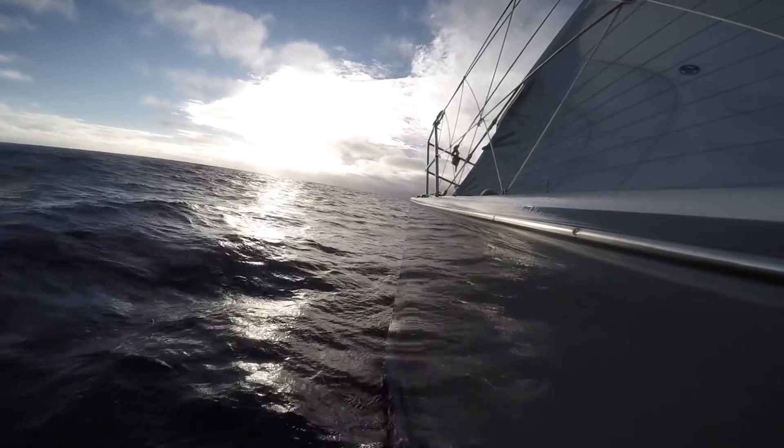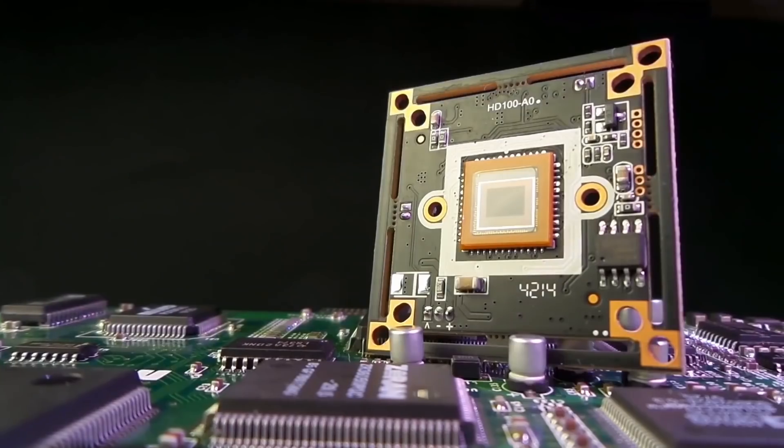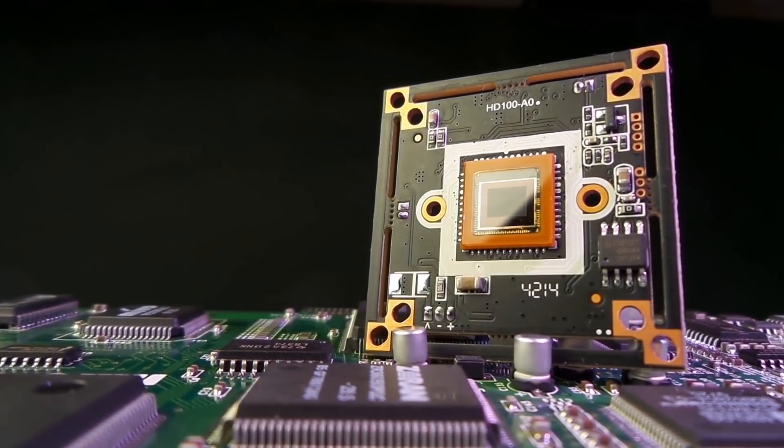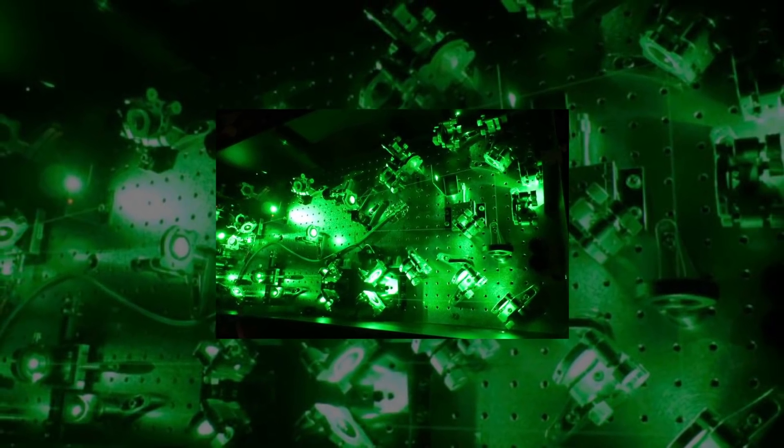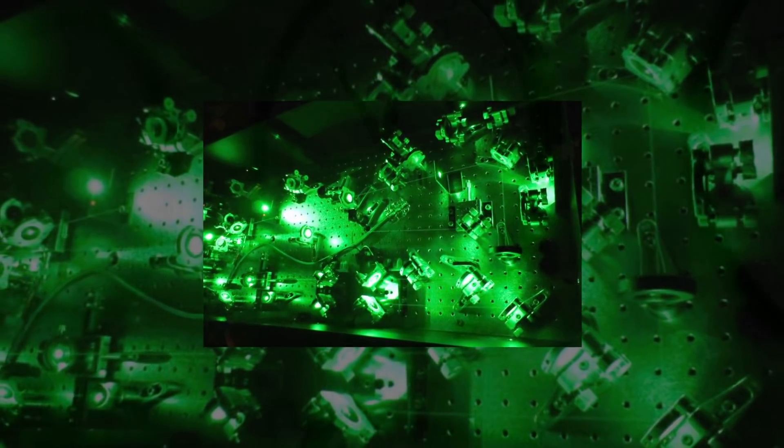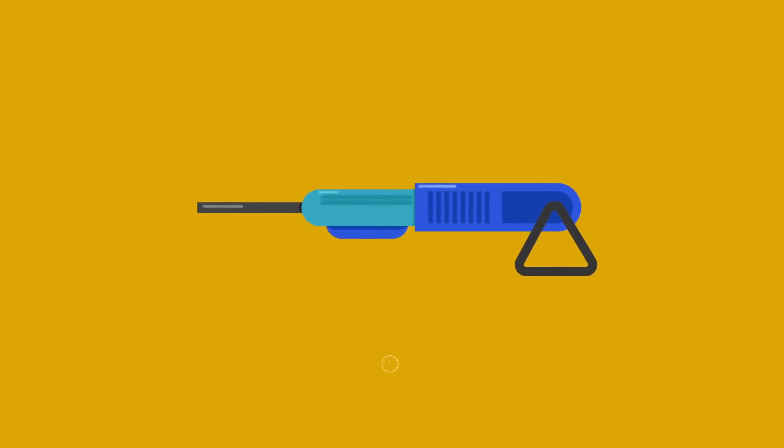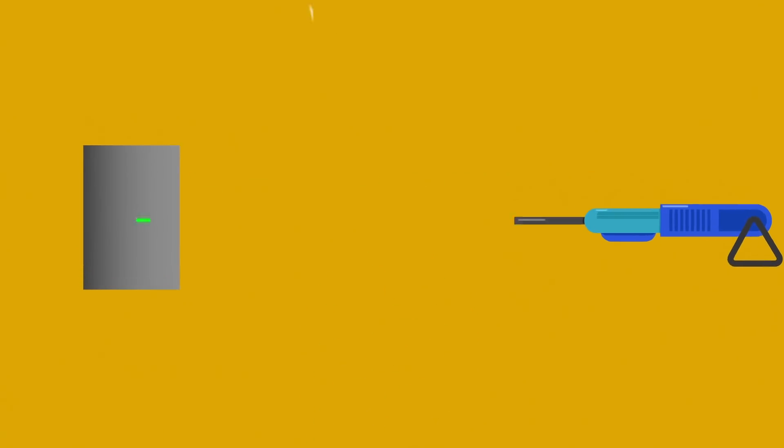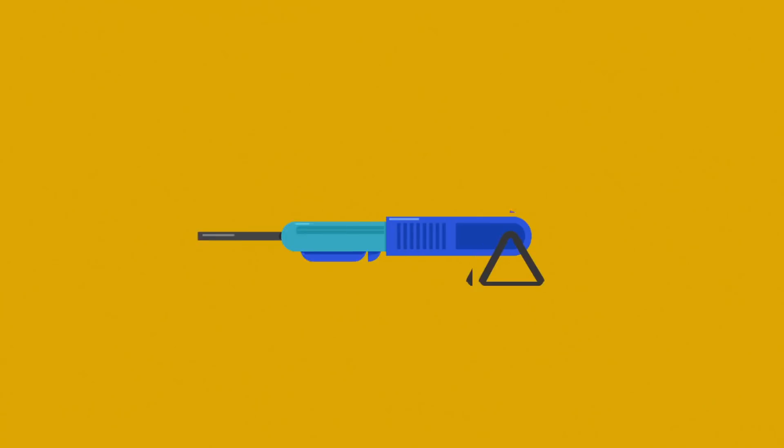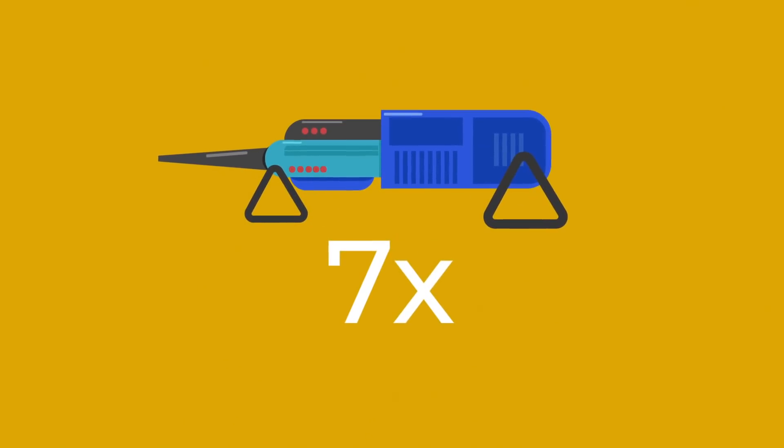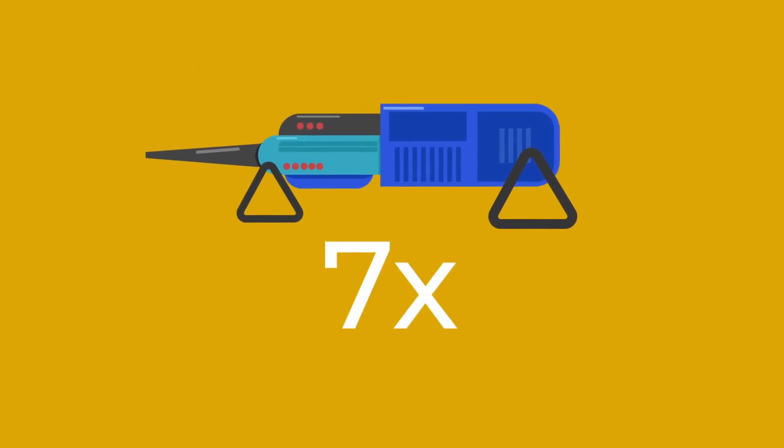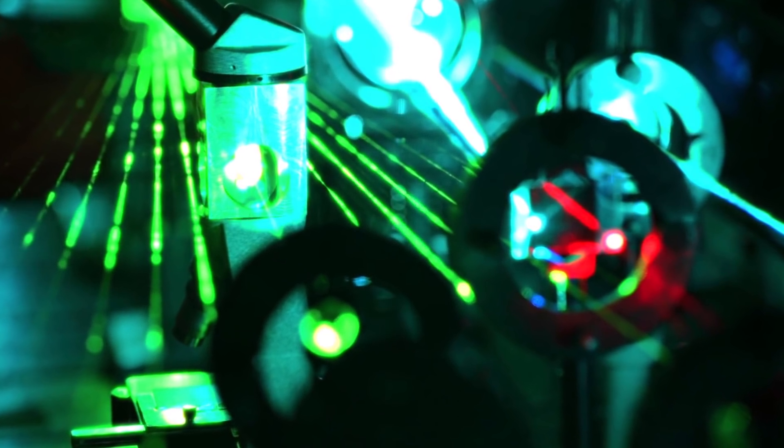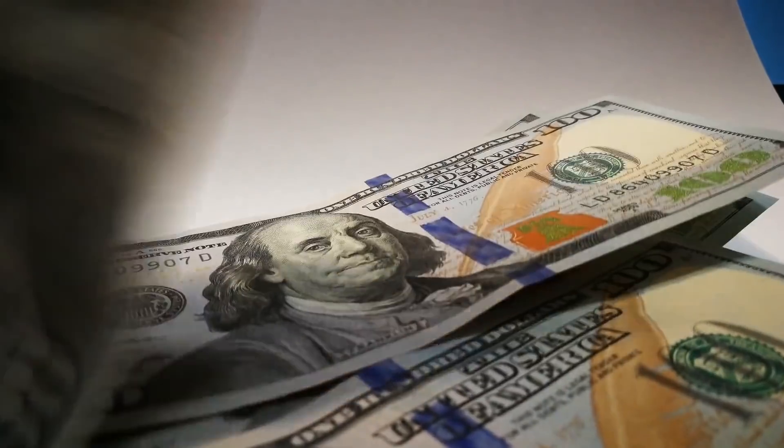Unsinkable metal can push shipbuilding and electronics far ahead into the future. The only problem is that the laser etching process itself takes an extremely long time. When Guo's laboratory first demonstrated it, it took an hour to apply a pattern on a surface measuring just one square inch, or 6.5 square centimeters. Now, thanks to the use of lasers that are seven times more powerful than the original ones, the laboratory has been able to accelerate the process, making it more suitable for expanding to commercial uses.